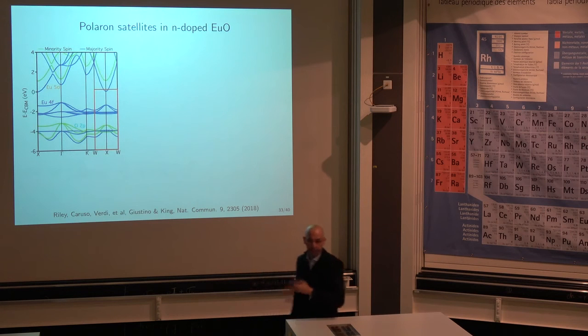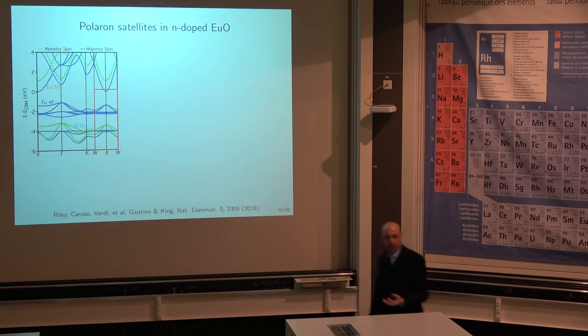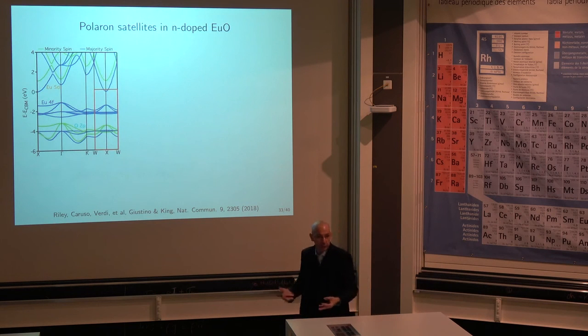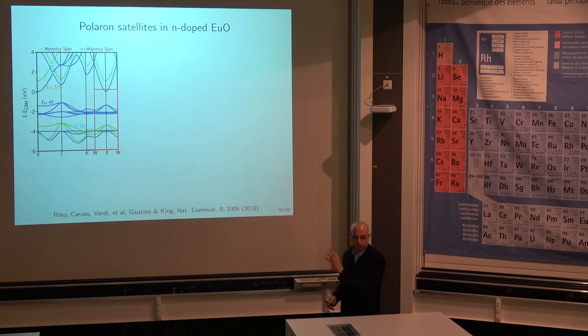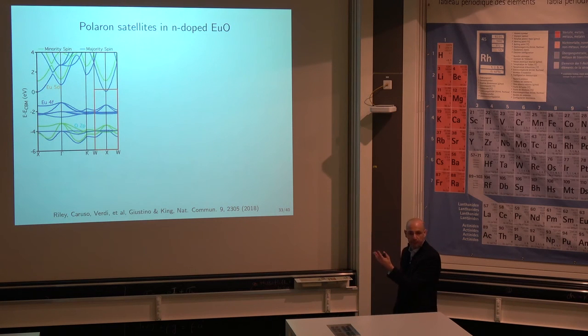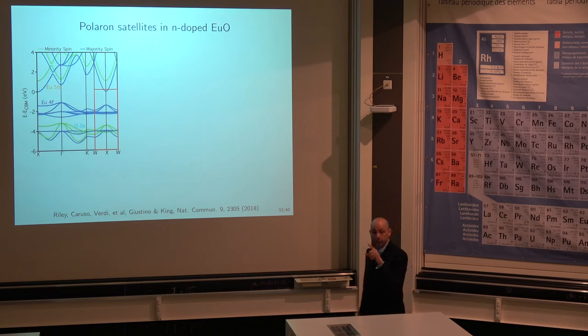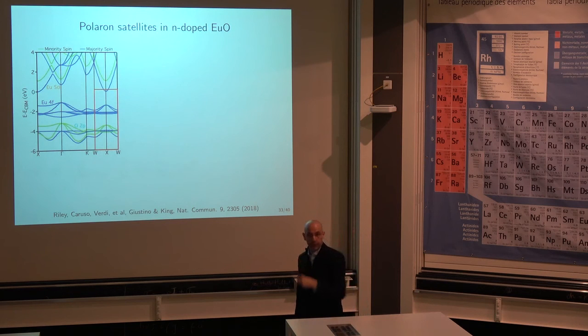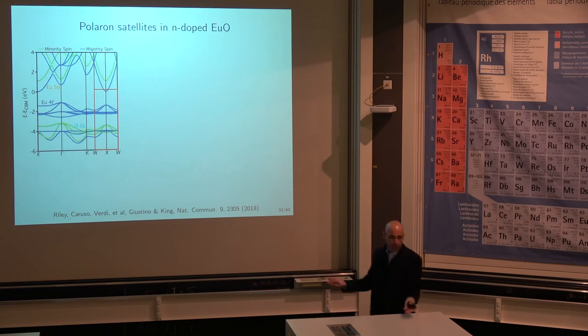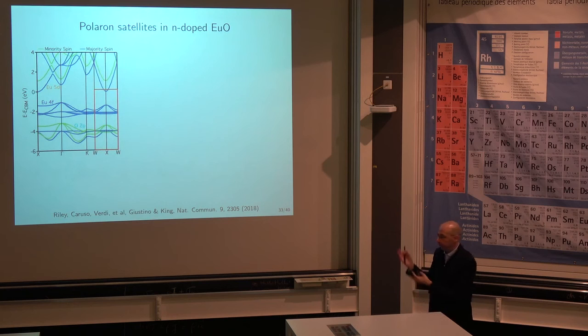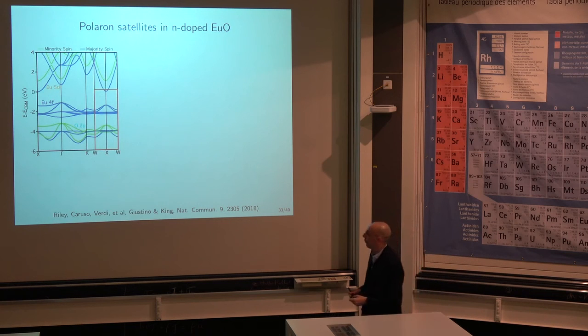So that's why it became kind of fashionable a few years ago, because it was essentially the first fully spin polarized semiconductor, and you can use it in principle for spintronics. The problem is that if you oxidize it, it becomes europium sesquioxide, Eu2O3, and if you go above 60 Kelvin, it's no longer ferromagnetic. So for practical application, it's not going to work, but it's an interesting proof of principle.